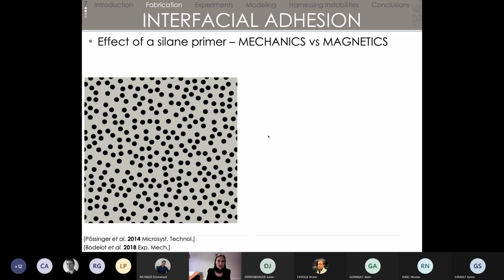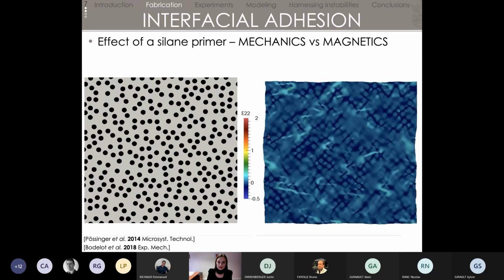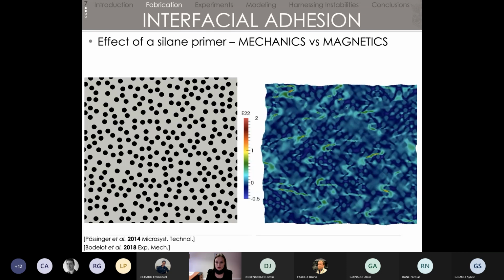So here you have a soft matrix and some particles inside, and then you're going to apply a large magnetic field. And you can see that locally, all those red dots here, you can have up to 200% strain locally around the particles, which explains why we see a significant debonding under magnetic field.